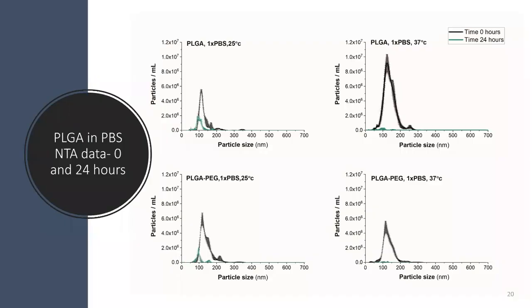So next, we went on to use nanoparticle tracking analysis to look at how the PLGA nanoparticles behave when we incubate them in phosphate buffered saline. This is essentially salt water with additional phosphate, and it's quite nice and boring. So what we see here is a distribution shift over time. More and more larger agglomerates are formed, but what this doesn't show is the formation of a protein corona. It's impossible because there's no protein in phosphate buffered saline.